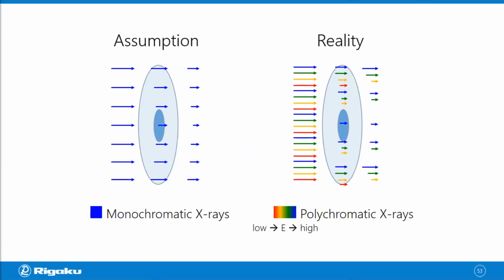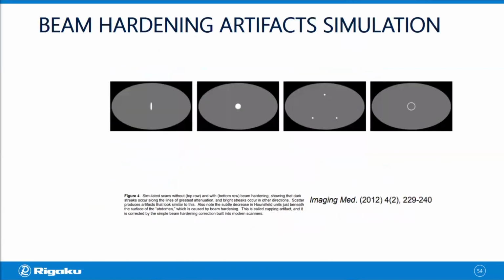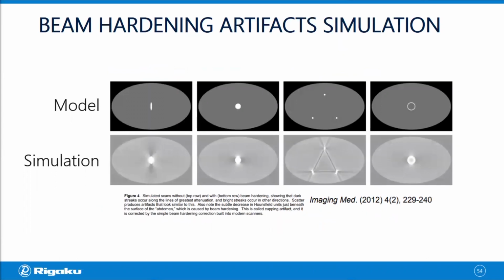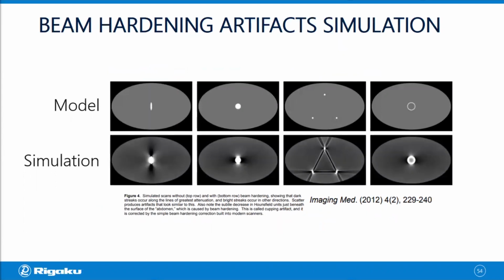But it is important to know what they look like so that when you see one, you would recognize it as an artifact. So those four cross sections are models we're going to use to do X-ray CT simulation. And the white areas represent high density areas that can often cause beam hardening artifacts. If you do CT scan for those cross sections, you're going to get something like those.